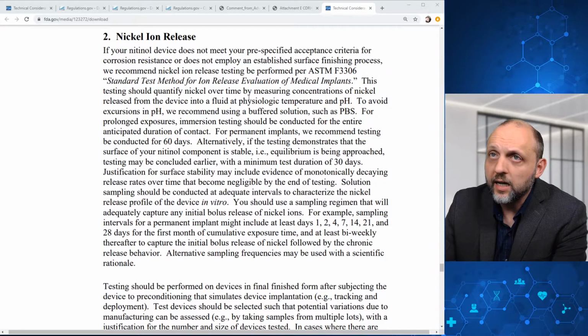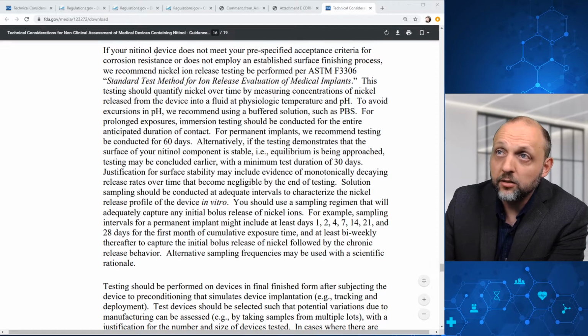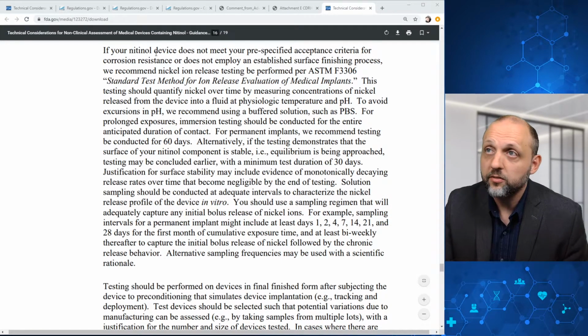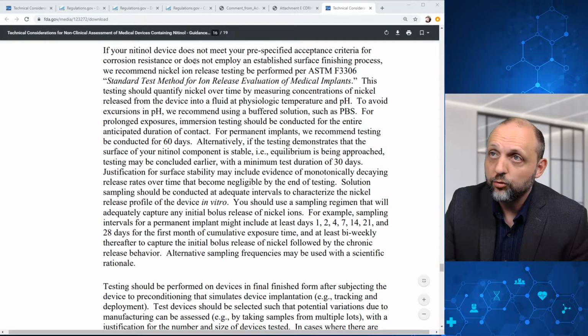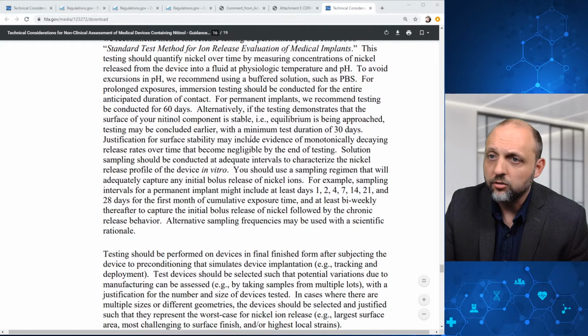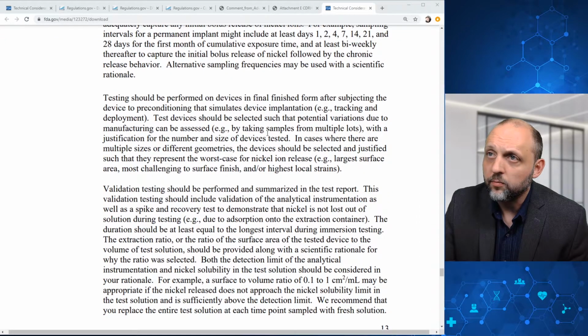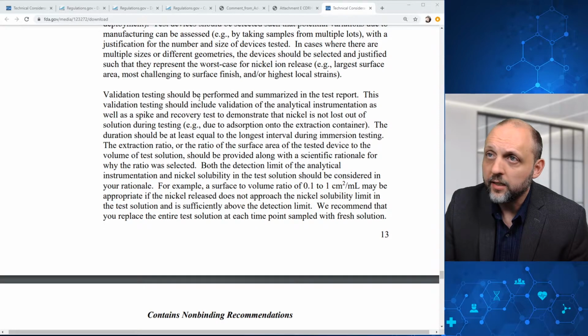And then in terms of nickel ion release, if your nitinol device does not meet your pre-specified acceptance criteria for corrosion resistance or does not employ an established surface finishing process, then FDA recommends nickel ion release testing be performed per ASTM F3306. Some details are included here about what that testing should look like. And again, testing should be performed on devices in final finished form after preconditioning. And again, the validation testing should be performed and summarized in the test report.